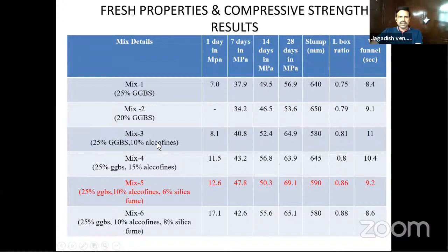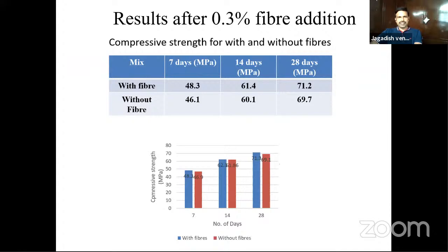25% gives more strength, so we used 25% GGBS and 10% Alccofine. With 15% Alccofine, 10% was optimum, so we used 10% again, and we tried 6% and 8% silica fume. Out of these, 6% silica fume gave the optimal mix. So this mix 5 we have taken as the optimal mix with the various powders, SCC. Then we started adding the fibers at different quantities.